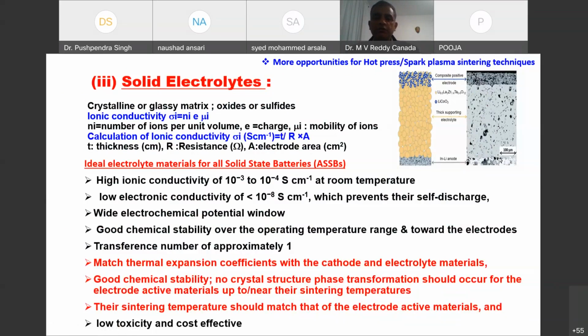There are a few challenges: if you go for high temperature sintering, there is reactivity at the interfaces, and sometimes you may reduce the conductivity. Also, if you want fast charge and discharge rates, there are a few difficulties. We also have to look into chemical stability, cost and toxicity. We are not really bothered about this in the initial stage, although people are still putting in further cost. Sometimes they use polymer membranes, but with polymer membranes the conductivity may be reduced.